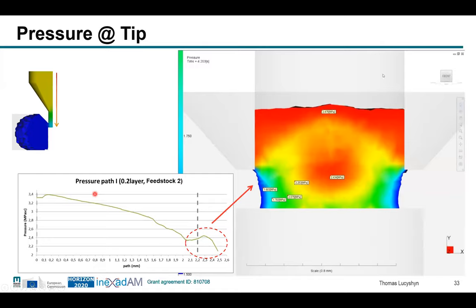Typically, going through a nozzle, you would see a decreasing pressure from the beginning of the nozzle to the end of the nozzle where it comes out. But we saw here some strange peak, which was then explained because the material is flowing here, and then it goes against the opposite wall, and there is some kind of stagnation zone, and some hydrostatic pressure building up here, which increases the pressure again towards the end.